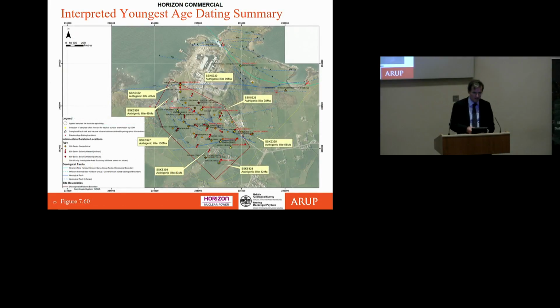Okay, then we plot those up of where we've got those age dates from different parts of the site. So you can see, as I showed in a figure earlier, we took the samples from right across the site and from faults of different orientations, and we consistently get these youngest ages are pretty old actually. They're in the order of 35. The youngest was actually 38, but there's plus or minus a couple of million years, and up to about 75 million years old at the site.